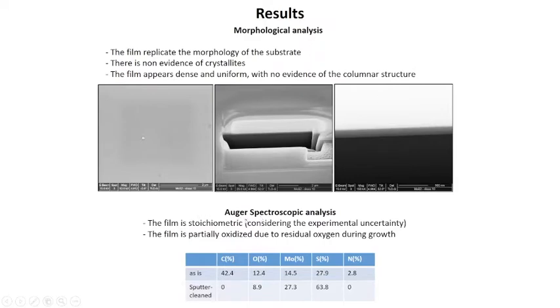By means of Auger spectroscopy, we also characterized the stoichiometry of the film, and looking at the table, you can find that the film is stoichiometric. We have a small amount of oxygen, which is related to partial oxygen inside the chamber, but looking at the spectra from the Auger spectroscopy, we may say that oxygen in this case is a residual oxygen inside the chamber.